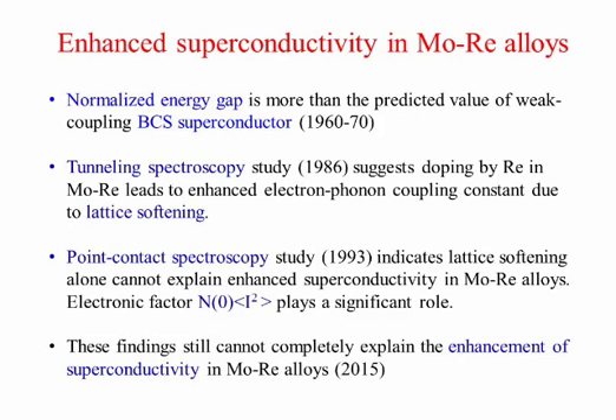Experimental studies done in the mid-1980s and early 1990s suggested rhenium influences softening of the phonon spectrum and a change in the electron density of states in the molybdenum-rhenium alloys. But this phenomenon could not completely explain the reason behind the enhanced superconductivity in molybdenum-rhenium alloys.